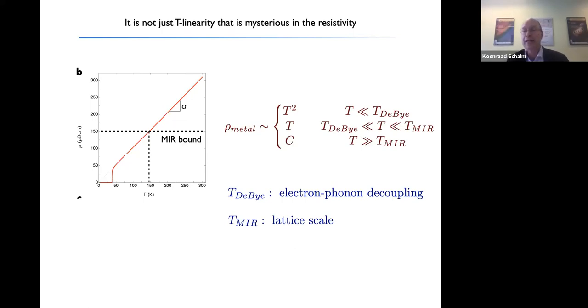And then there's a third classic transition in ordinary metals, the so-called Mott-Ioffe-Regel limit, above which the resistivity saturates and becomes a constant. The Mott-Ioffe-Regel limit is roughly speaking where the scattering length becomes of order the lattice spacing in the system, and then phonons, which are the main reason for resistivity in ordinary metals, can no longer become stronger because below the lattice spacing there are no extra phonons in the system, and so you saturate. But precisely these types of transitions, and there could be even transitions due to smaller effects, you don't see in strange metals. And this is in itself a mystery.